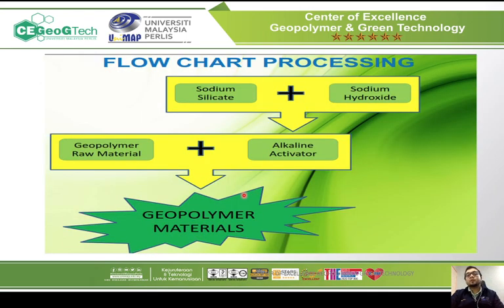This is the flowchart for the processing to make a geopolymer. Firstly, we produce the liquid one, which is sodium silicate mixed with sodium hydroxide, to make the alkaline activator. After that, we mix it with the geopolymer raw materials that I mentioned before, such as fly ash, white clay, silica sand, dolomite, and so on. So we mix the solid and the liquid, and it becomes the geopolymer material.